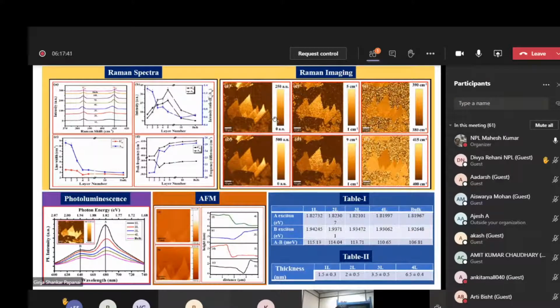And to see the uniformity of these two vibrations at different locations of the sheets, we perform the Raman mapping. The Raman mapping here shows the intensity of the E1 2G vibration, and this is the peak width and this is the peak position, and you see the different contrast of the layers here. In both figures you can compare, and it is very easy to distinguish the different layers.